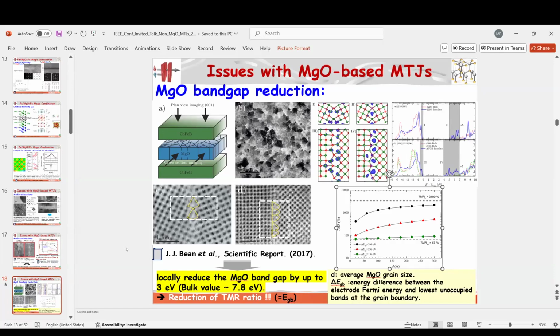Normally, the TMR should increase with the thickness, because for very thick MgO in antiparallel configuration we are nullifying the conductivity. But what happens in reality is that the TMR saturates with the thickness, and this is one of the reasons.